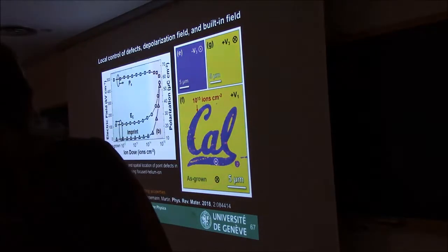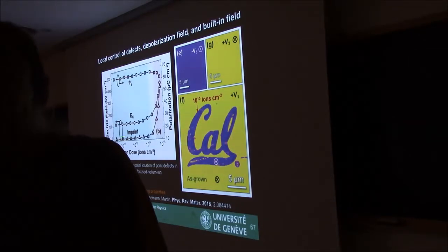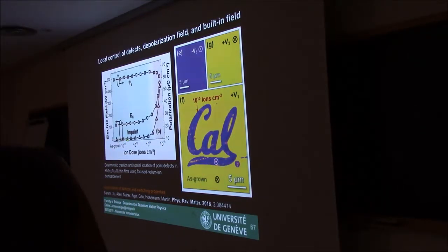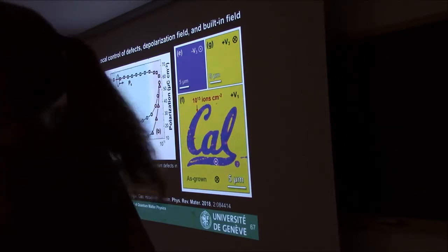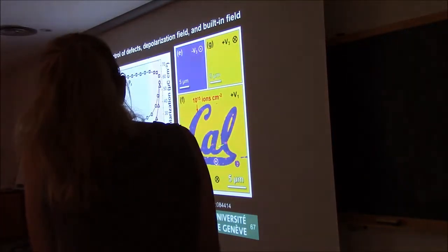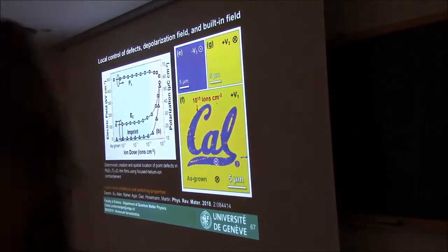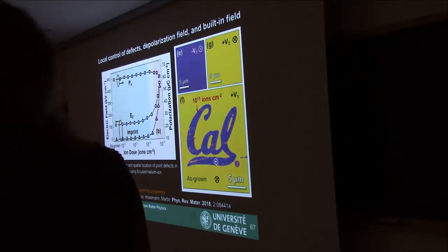And when they measured the coercive field and the imprint, so this built-in field, they also see that for a large enough dose of these point defects, they can change this coercive field and the imprint. But what I find very nice in this study is that it shows you that defects, of course, will affect the depolarization field and the built-in field, but also, because they were able to bombard locally, they locally implanted some point defects. And then locally it changed the built-in field.